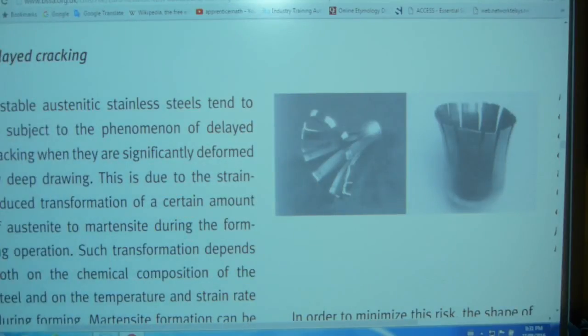Not anymore. And it splits like this spectacularly because of the delayed transformation of the austenite. And this one says, instead of delayed transformation, it says delayed cracking. Same thing. You can read it, and I'll show you where this PDF is. And it happens during deep drawing.